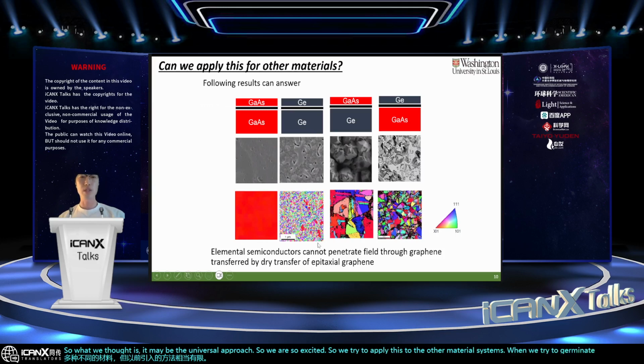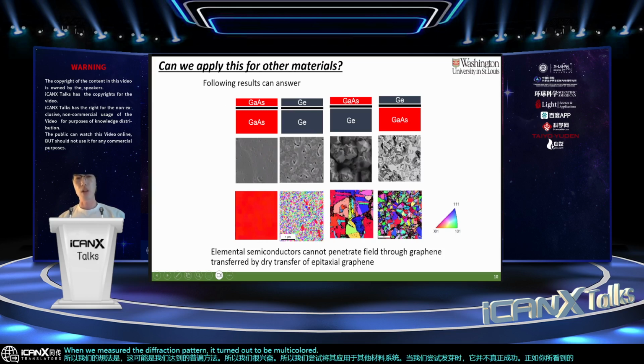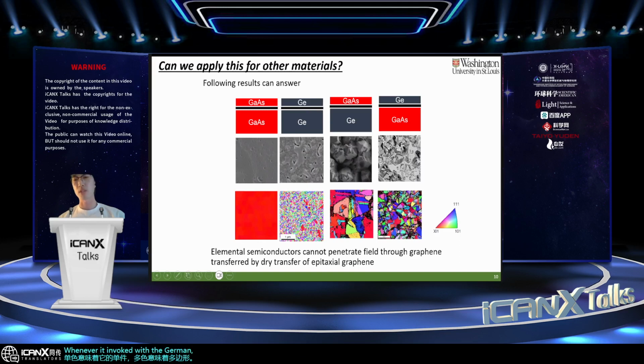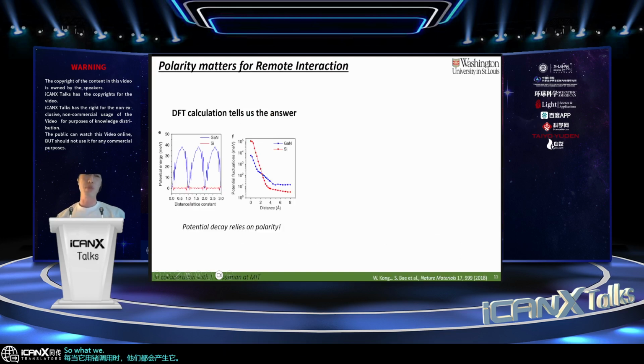As you can see, when we measured the diffraction pattern, it turned out to be multicolor. It's the EBSD color mapping. Monocolor is single crystalline, and multicolor is polycrystalline. Whenever germanium was involved, they all produced polycrystalline. We were kind of disappointed to see that result, but while trying to understand the situation, we found another interesting phenomenon.